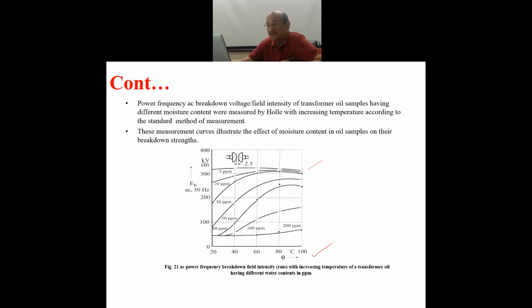But the humidity content increases over time. It does happen that when the transformer is under rain and different weather conditions, it has a humidity ingress property. Humidity is absorbed by the transformer. However you may try to prevent humidity from reaching the transformer, it does reach. So when it is of the order of 100 ppm and 200 ppm, the same breakdown strength of more than 300 kV per centimeter reduces to only about 50 kV per centimeter. What a drastic reduction in breakdown strength. And then it is not desirable to continue with the oil under such conditions. They must do something to purify the oil.